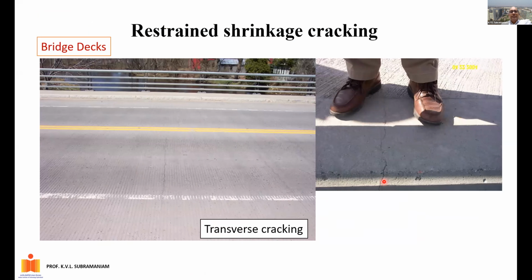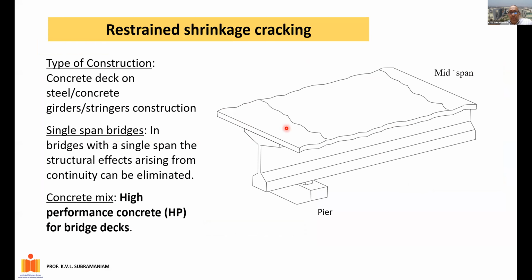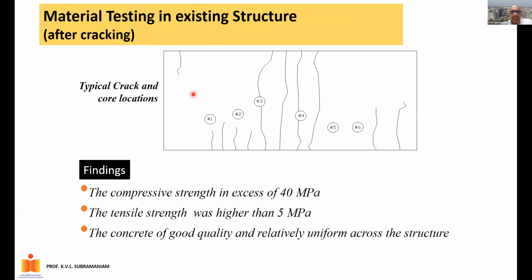is thoroughly cracked. Now, the reason for this does not have to do with structural configuration, or this is not a structural crack. The cracking was discovered to be basically running in areas. This is a simply supported bridge deck, and the cracking happened right in the midspan. So if I can just show you, this is the bridge deck. This is simply supported. All the cracking happened in the midspan, and this cracking happened in areas where concrete deck would be in compression. So it didn't make sense.